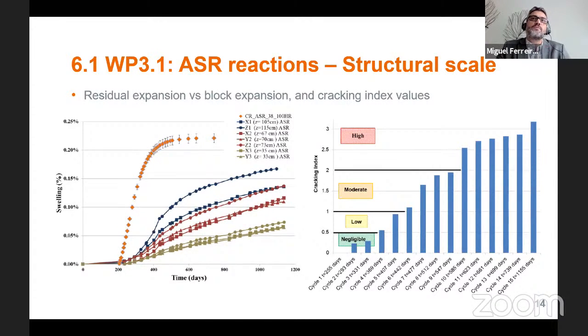These make it possible to assess the damage of ASR and whether this is going to get worse in the future or whether the expansion has stabilized. It's also one of the main data that is used in numerical simulations and allows us to calibrate the chemical processes of the reactions in the models. And it defines a kind of chemical potential of the ASR, defining an upper limit, a strain limit for the structure.